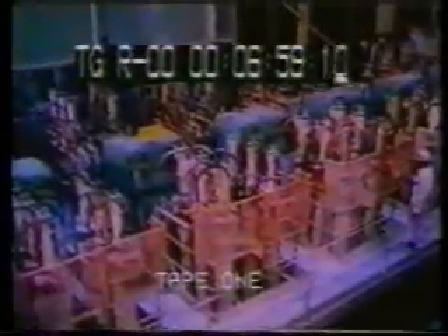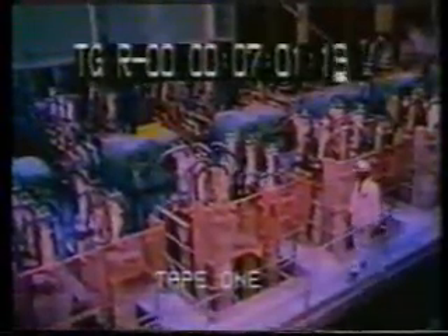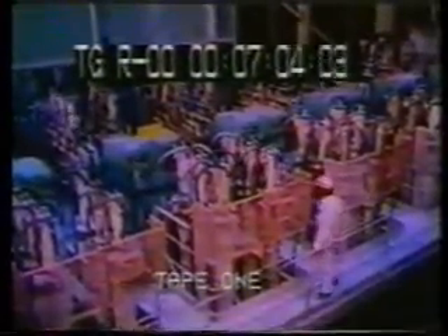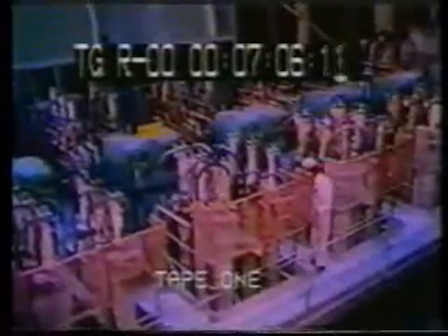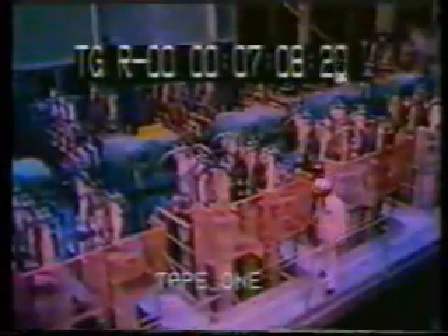The resulting powder, a calcined magnesia, is formed into pellets by high-pressure rollers exerting pressure of about 3 tons per square centimetre before being fed to the rotary kilns. This system, operating at pressures up to 140 atmospheres, produces a filter cake of 75% solids content, which is fed directly to the rotary kiln. This produces a pellet-type product without passing through the stages of Herreshoff calcining and pelletization.